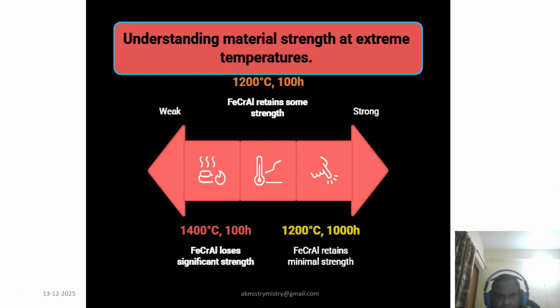And now, here is one of our summaries. The longevity benefits are substantial. Life expectancy at 1000 degrees centigrade furnace temperature is more than double that of a nickel chromium wire, as we have discussed, when used in a specific element system. Furthermore, the protective aluminum oxide film that forms acts as an extremely efficient barrier, as we have already mentioned, against high carbon activity. This provides a high resistance to carbonization, which is critical, and if hydrogen is mixed with carbon bearing gases, such type of element can take care of such a situation.